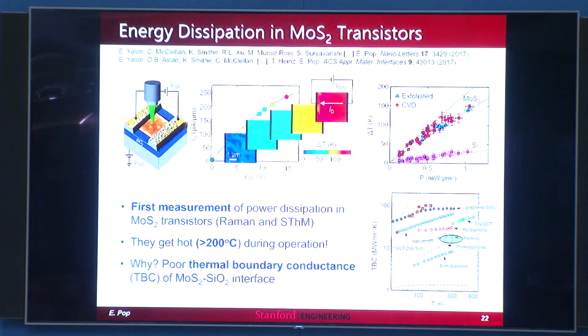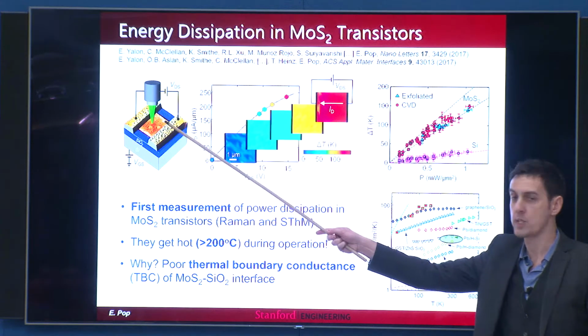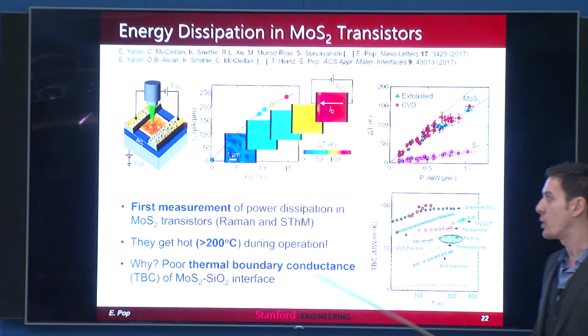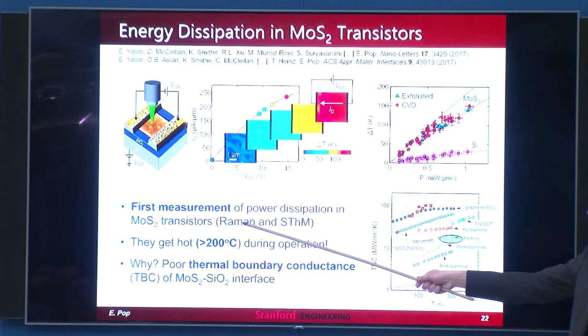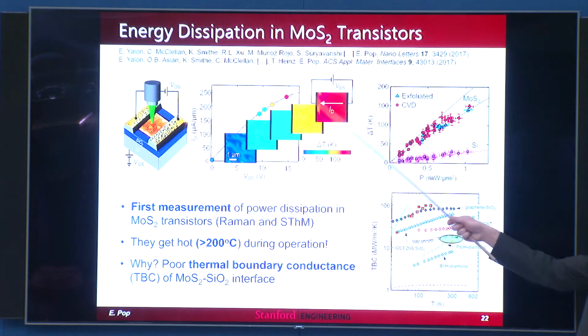OK. We have a habit in my group of doing thermal measurements. And in this case, this really was motivated by variability. We said, hey, we can measure the temperature of these devices during operation. But these devices have bilayer regions in them, right? And so we started taking these thermal images using Raman thermometry and scanning thermal microscopy, actually both, of these devices during operation. And what's interesting is, again, even by thermometry, we don't see the bilayer regions. That's good. That means the bilayer regions are not really hotter or colder than the rest of the channel. So that means that they're almost invisible in a way to electron transport, which again is confirming what I stated earlier.